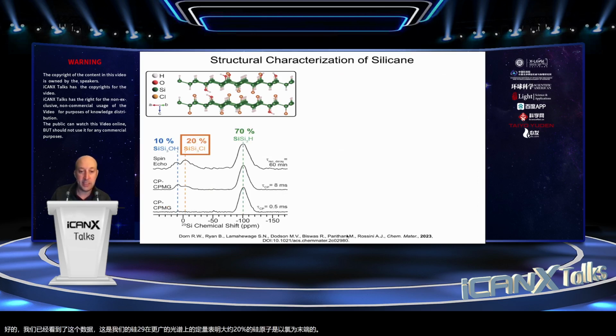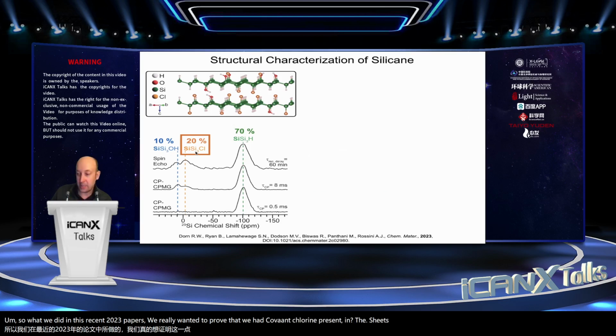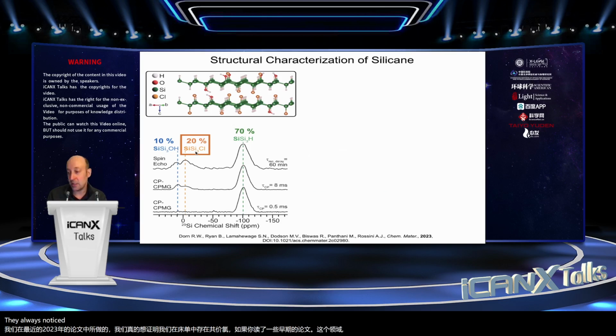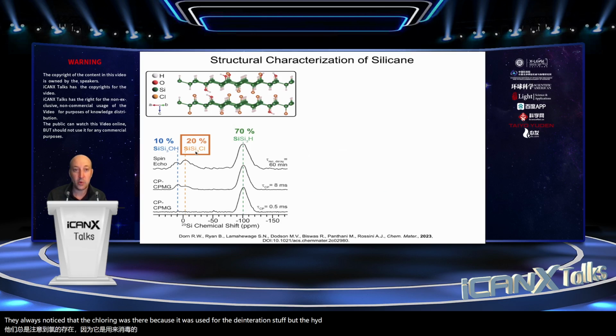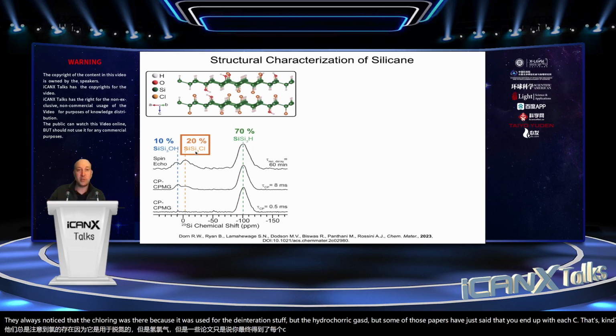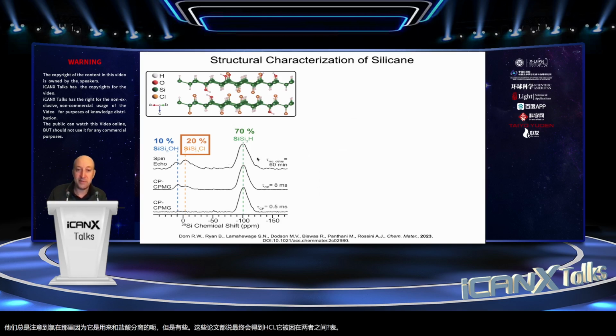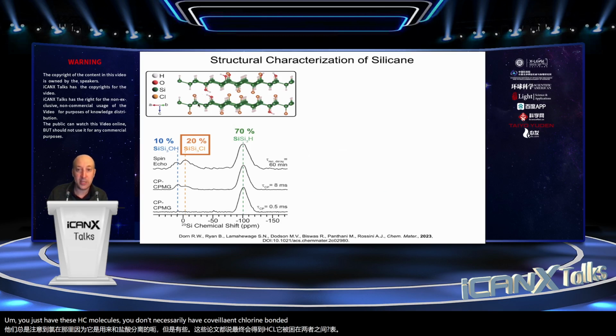So what we did in this recent 2023 paper is we really wanted to prove that we had covalent chlorine present in the sheets. If you read some of the early papers in this field, they always noticed that the chlorine was there because it was used for the deintercalation step with the hydrochloric acid. But some of those papers have just said that you end up with HCl that's kind of trapped in between the sheets. You just have these HCl molecules. You don't necessarily have covalent chlorine bonded to silicon.